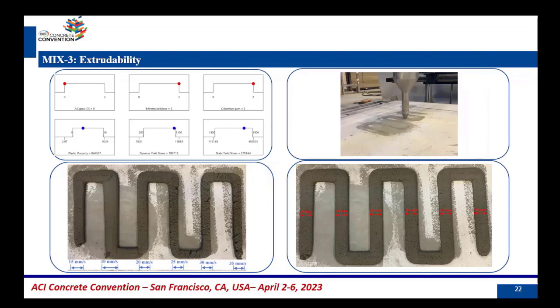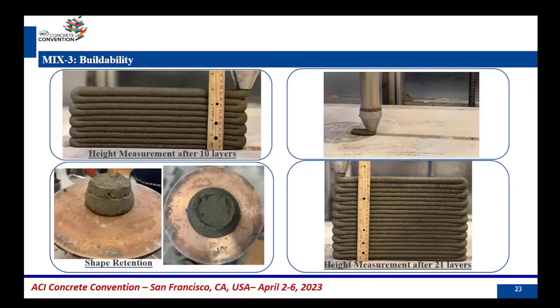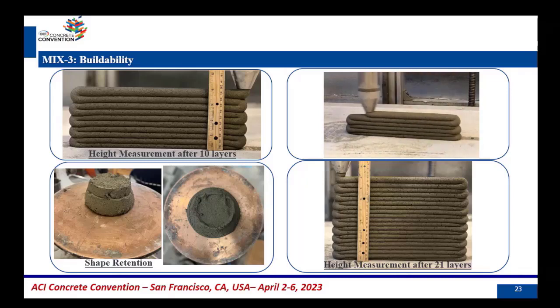About mix 3, again the optimized printing speed in this case was 20 millimeter per second. And again, you can see the quality of extrudability in terms of dimension consistency. The design dimension was 30 millimeter, and we were able to achieve that exact dimension with a printing speed of 20 millimeter per second. For the buildability, again, this mix was printable up to 21 layers, and it collapsed after printing the 21st layer.